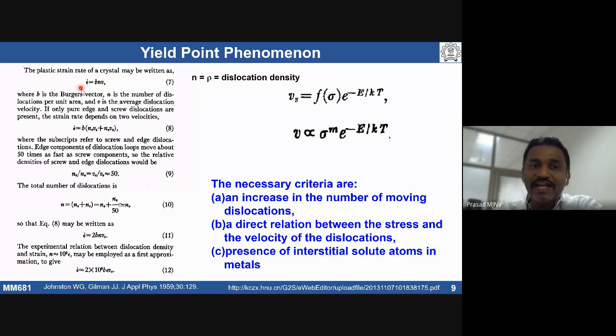So the local strain rate, when you are applying deformation at a certain rate, but locally the rate of deformation is going to depend on dislocation velocity and dislocation density. If you take a representative volume in a material, I'm deforming material at an external strain rate, some epsilon dot s, I'm deforming at a particular rate. But locally, the local strain rate in any given volume of a material can be taken from the Orowan equation. Strain rate is basically a function of dislocation density and dislocation velocity.